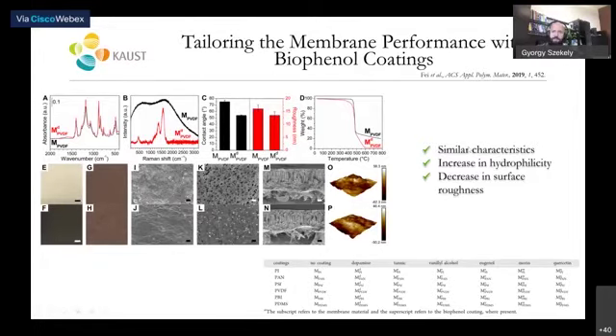So in general, we can say that we have a similar characteristic for all the membranes, independently of the polymer and the coating. And the coating increases the hydrophilicity of the membranes, and the surface roughness decreases.